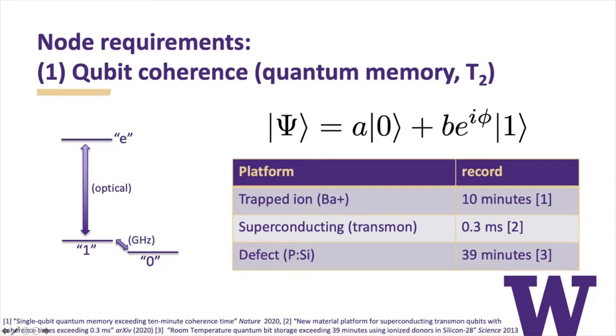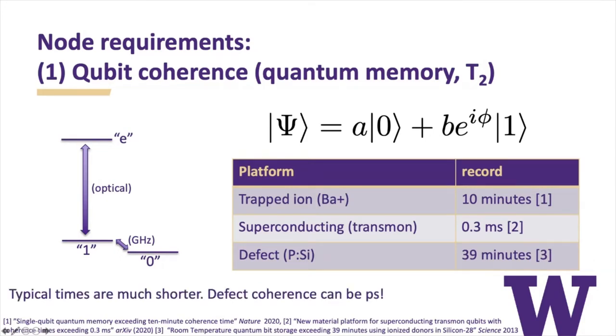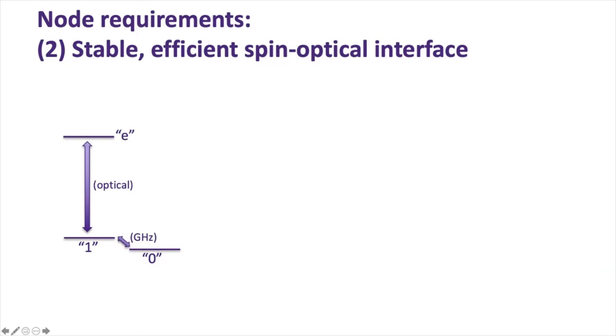Now, just like there's many different trapped ions and different geometries, and there's different types of superconducting qubits, these are just the records for one type. This is the record for one particular defect in a very, very pure material. This defect does not have the optical transitions that we want for network applications. It's a contender for non-networked quantum computing applications. Defects themselves in crystals can range from picoseconds up to these minute time scales. So there's a huge range depending on the defect and type of material of what type of quantum memory you can have.